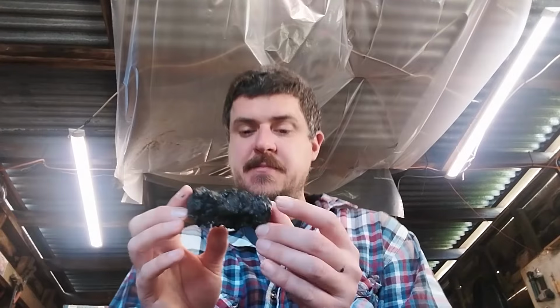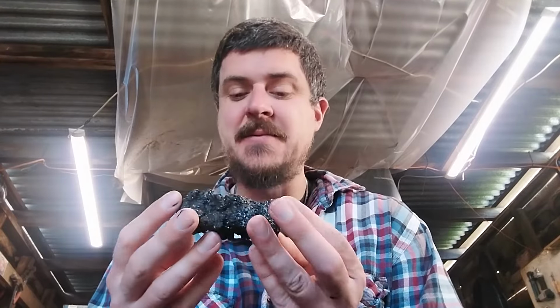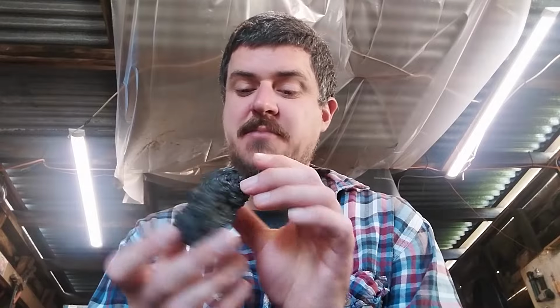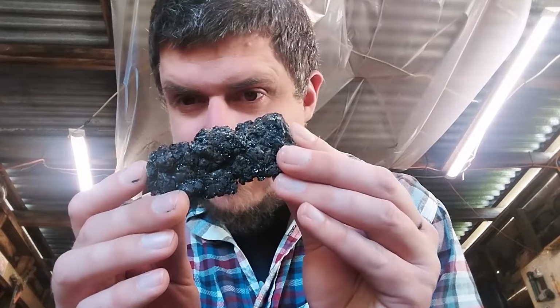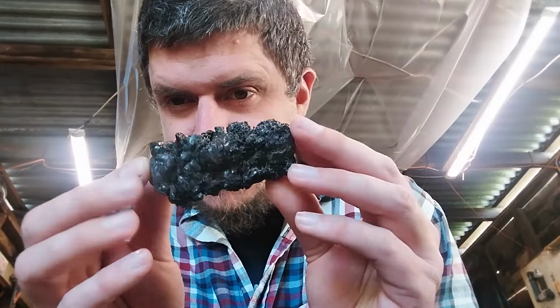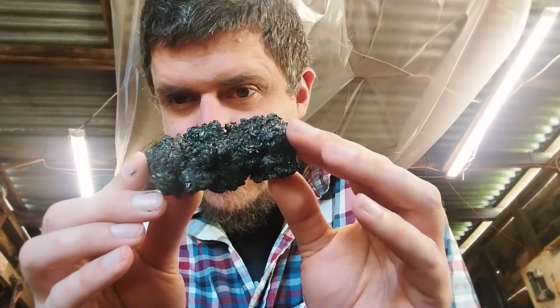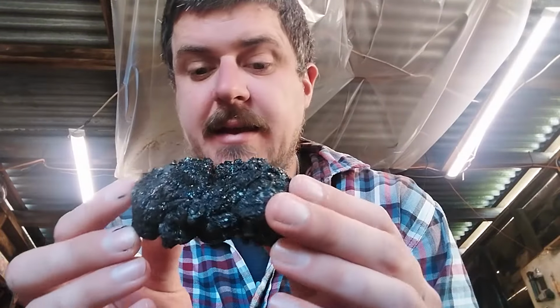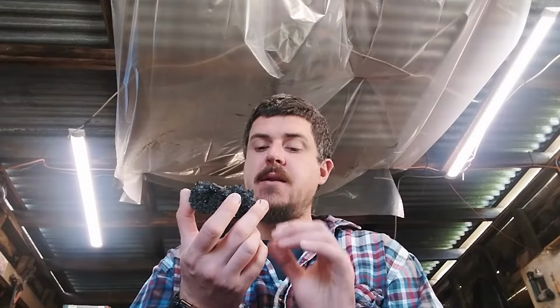So what do I mean by that? This is quite heavy, which means that the core is probably pretty good, but you can see that the surface is all sort of crackly and void filled, and still has visible slag in it. One myth is that in order to refine wrought iron, you need to get rid of all of the slag. And actually, that's quite incorrect. You want slag in there. What you want to do is control both the arrangement and the amount of slag. And we'll get to that because that's in the refinement process.